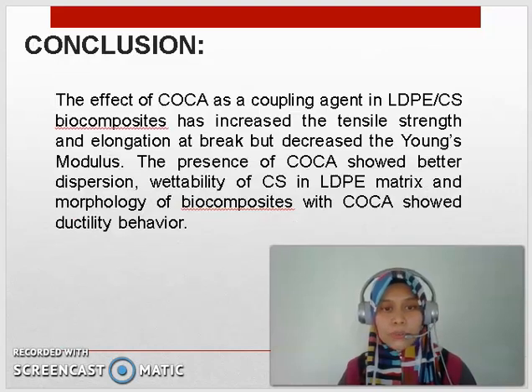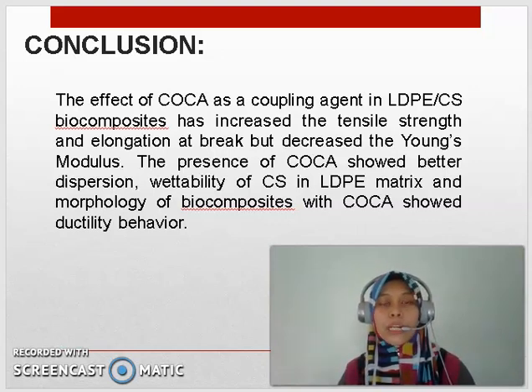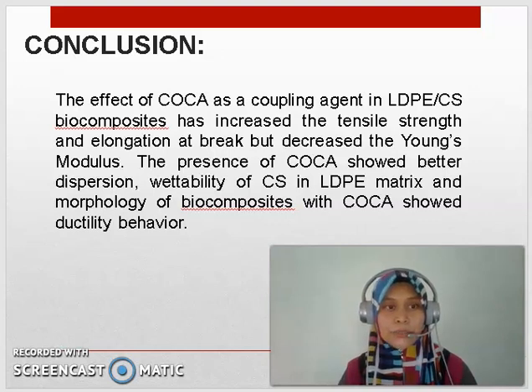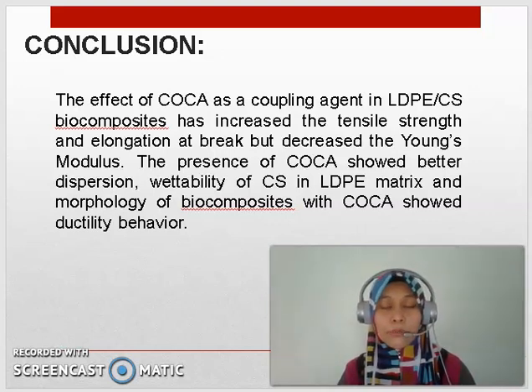As the conclusion, the effect of COCA as a coupling agent in LDPE or CS biocomposites has increased the tensile strength and elongation at break but decreased Young's modulus. The presence of COCA showed better dispersion and wettability of CS in the LDPE matrix, and the morphology of biocomposites with COCA showed ductility behavior. So, that is our research.